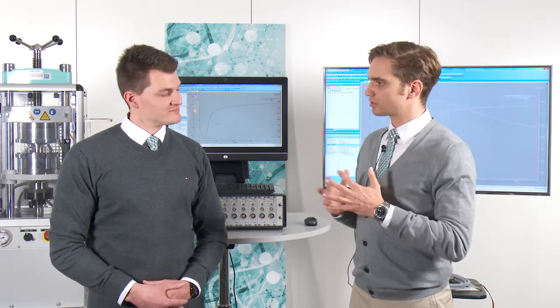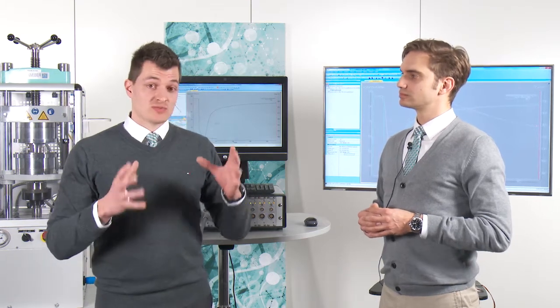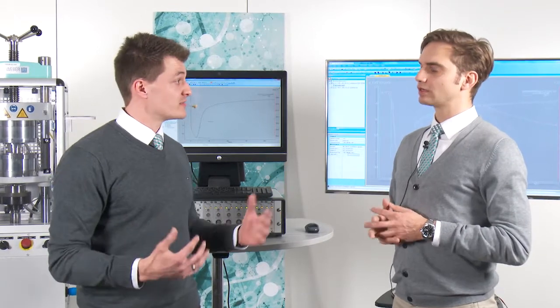Starting with the first question, Alexander, we use an epoxy system here. What about polyurethanes? Can I also look at curing of polyurethanes with the DEA? Yeah, for sure. You have dipoles in polyurethane systems. You have mobile charge carriers. So two effects we can measure with the dielectric analysis. So as well as this epoxy system we observed today, we can also measure polyurethane systems. Okay, so you get a very nice signal and you can also do that.